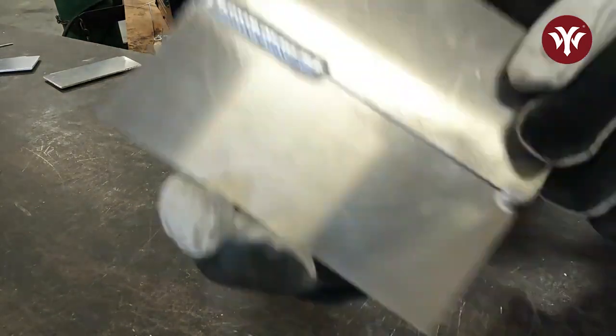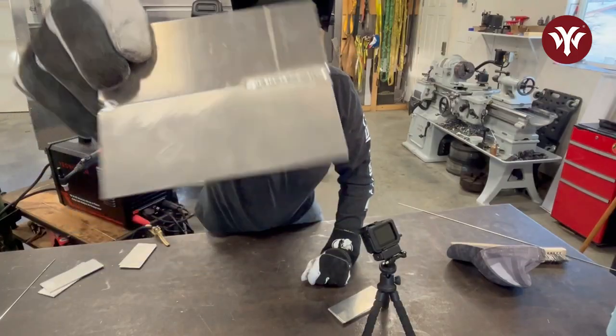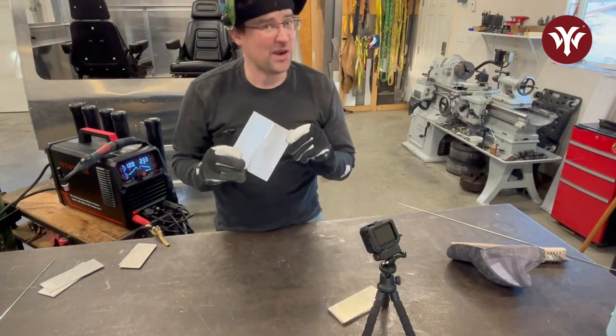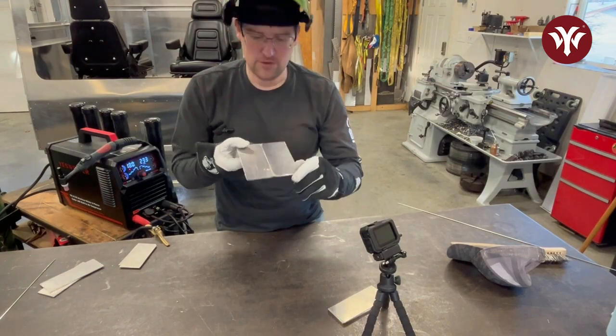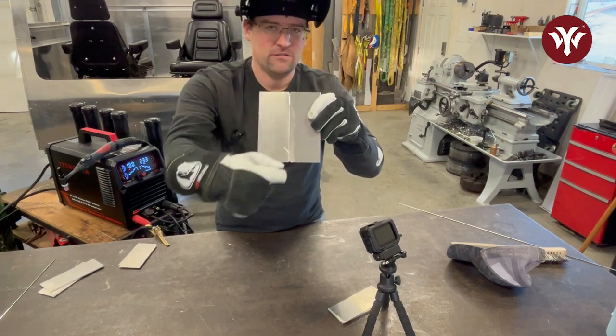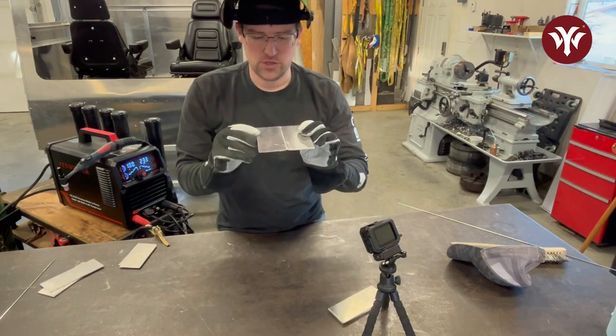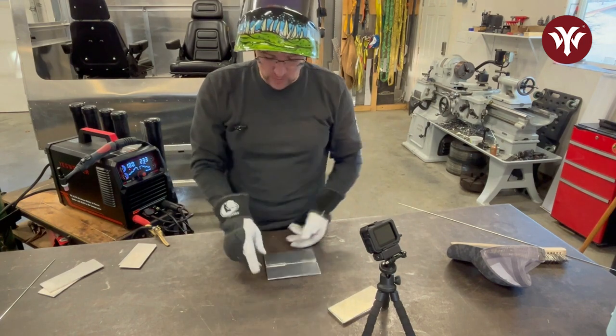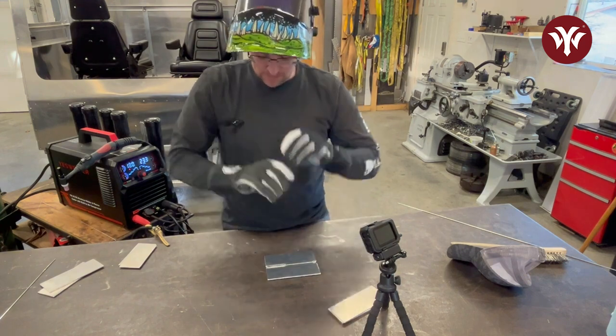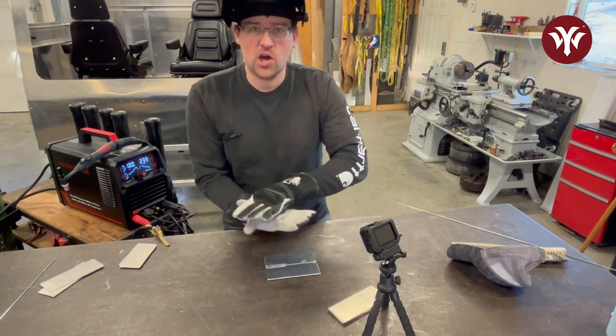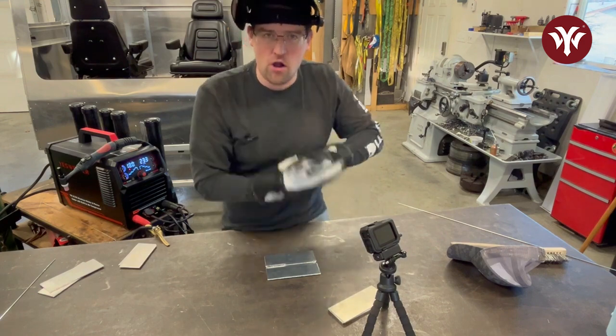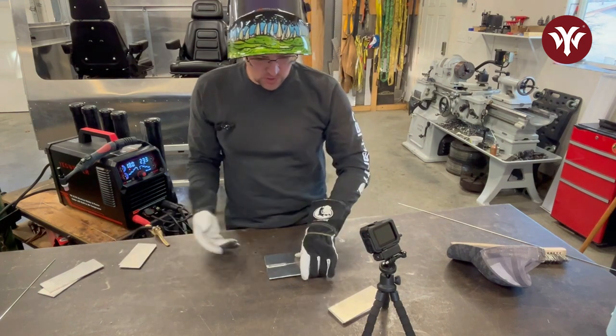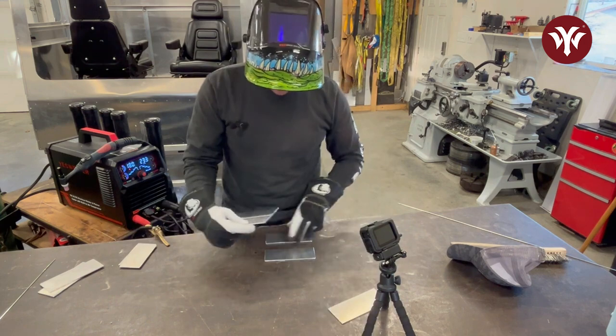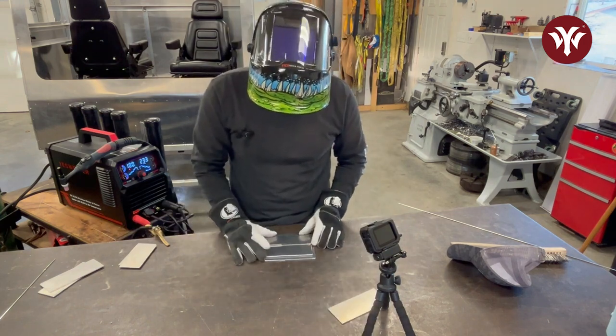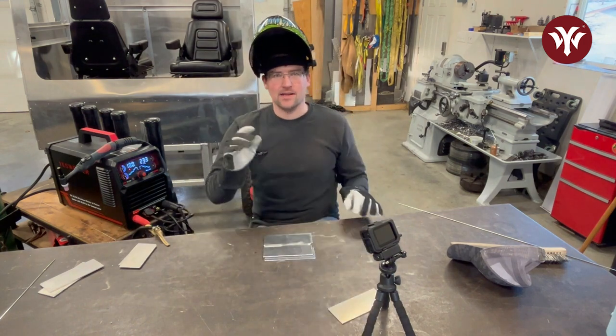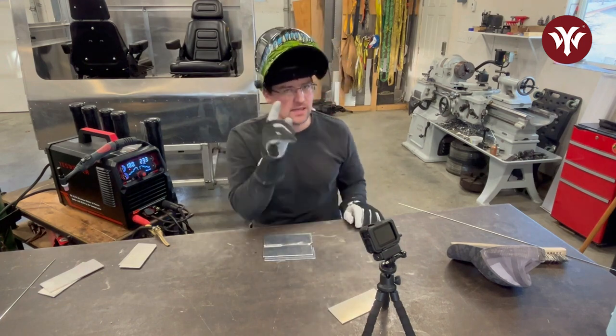Alright, show you there. The machine can weld really nice. If you notice the backside though, very little penetration. And I do believe that was largely to do with this table. Even though I got a molten puddle on top, the bottom side of that aluminum was getting all of its heat stripped away. So I want to go ahead, stack this off, and let's keep going, and I'll show you what that penetration on the backside should look like.